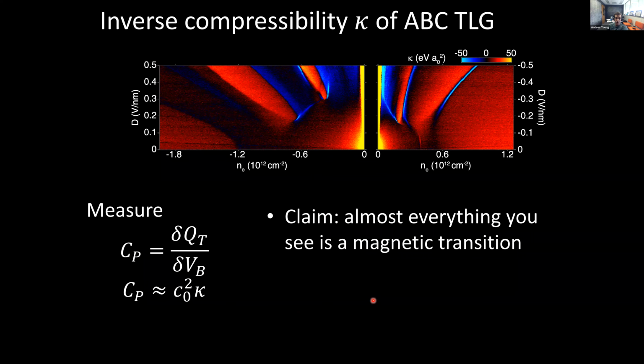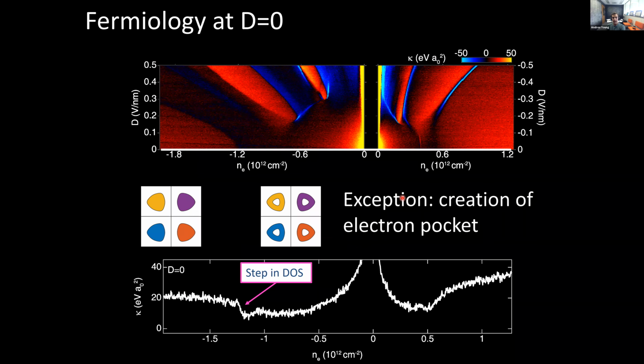So the claim that I'll make is that almost everything you see here is some kind of magnetic transition in these low energy bands of ABC graphene. Okay, and there's some exceptions. So for example, there's a feature here that we can actually identify with the creation of an electron pocket in the hole Fermi surface that's well described by a single particle model. So you see that there's a step in the density of states and a step, therefore, in the inverse compressibility, and it lines up very well with where you expect to go from having Fermi surfaces that are simple to Fermi surfaces that are annular.